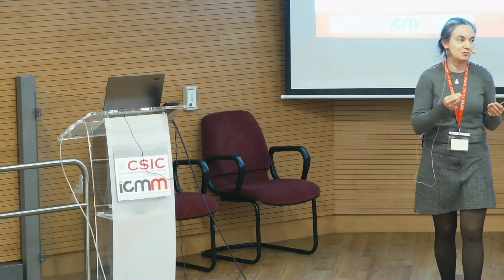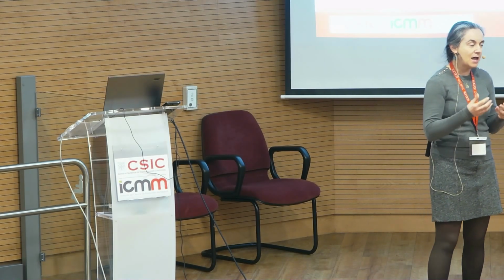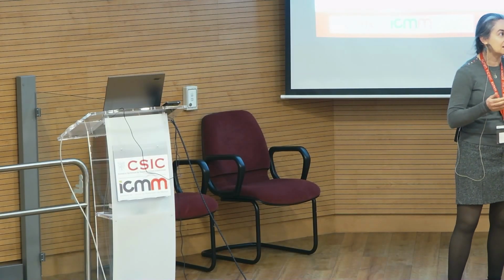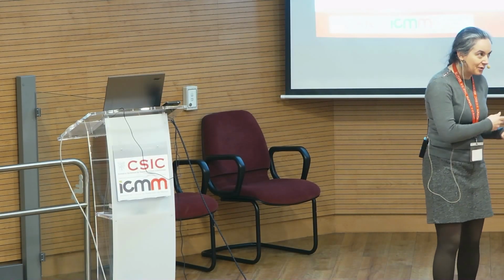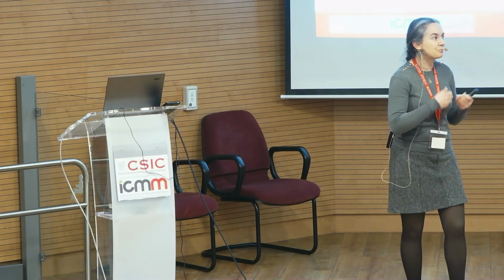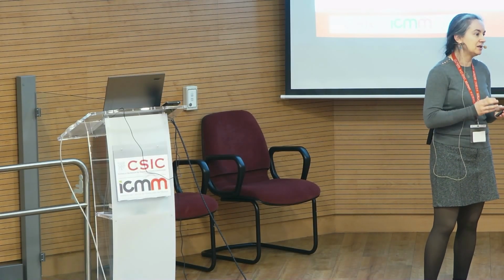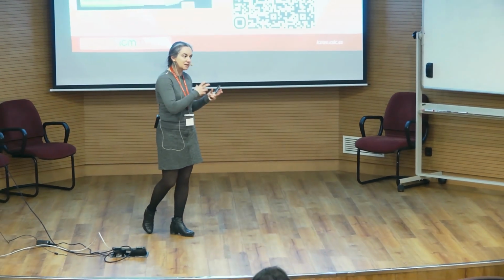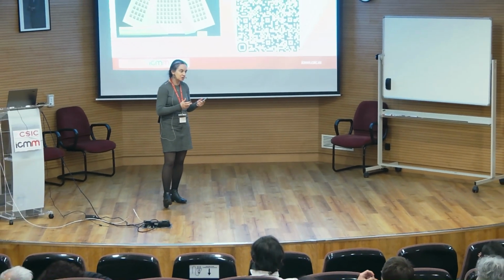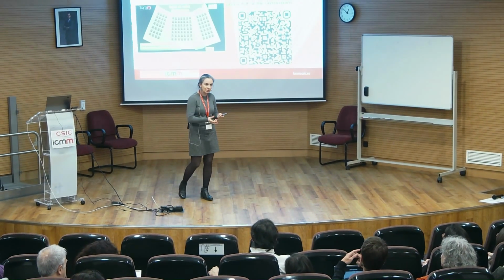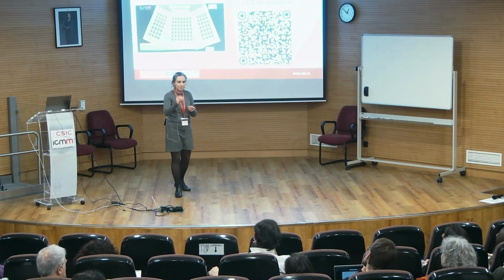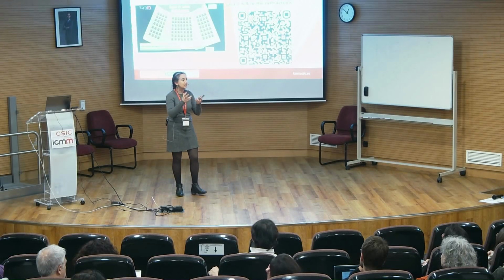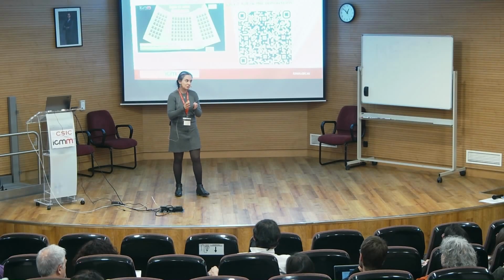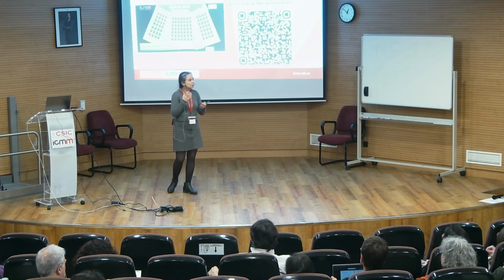We haven't been able to really demonstrate what is in there that makes it different from others. From our experience, of all the materials that we have tested, agarose, gelatin, graphene oxide in the shape of microfibers, many different variants, none of them has provided better responses than just the reduced graphene oxide by itself. We are now testing, in the project, this scaffold supplemented with the therapeutics that we are developing, the iron oxide nanoparticles functionalized with interleukin-4 that I was explaining, together with some nanotherapeutics specific for the piezo mechanoreceptors, all combined in the same scaffold, and we expect the response to be better. Because if just the scaffold was good, just having extra stimulus should be better, but not with other materials.